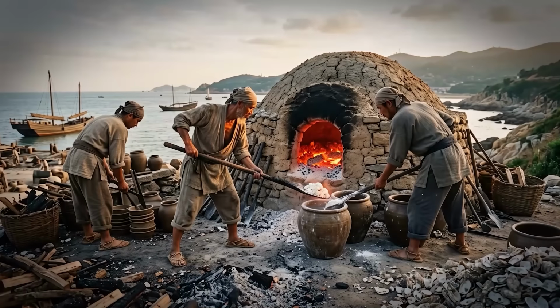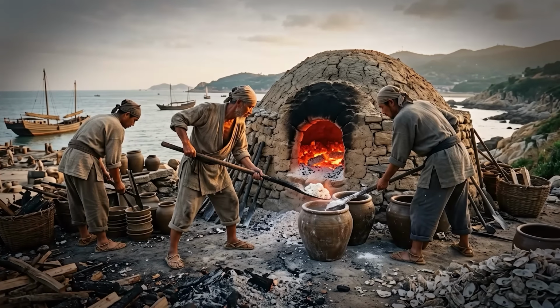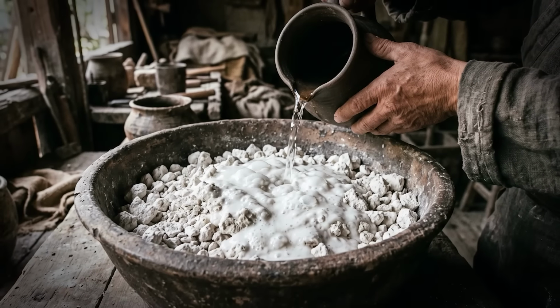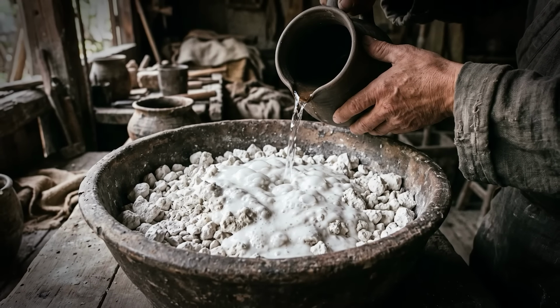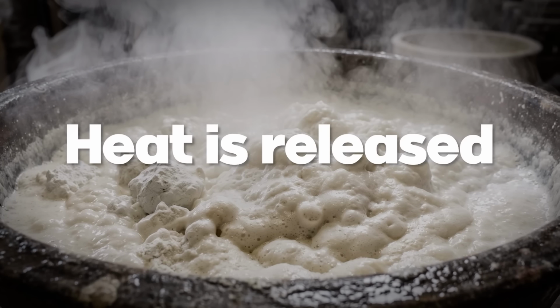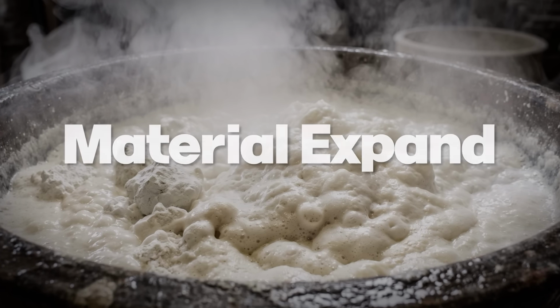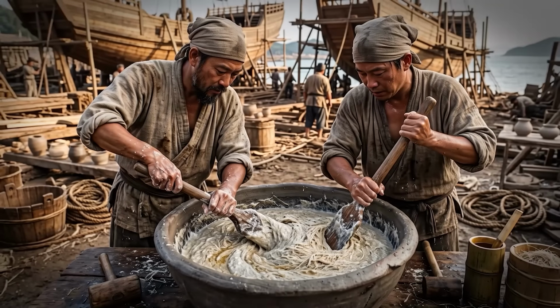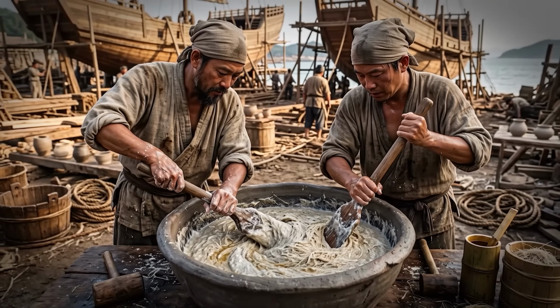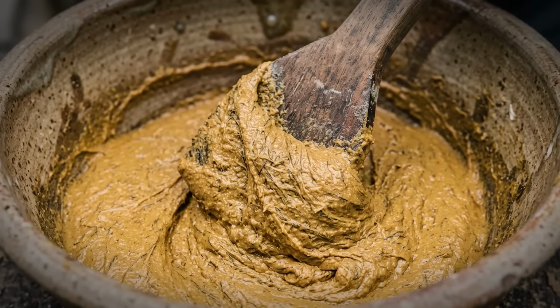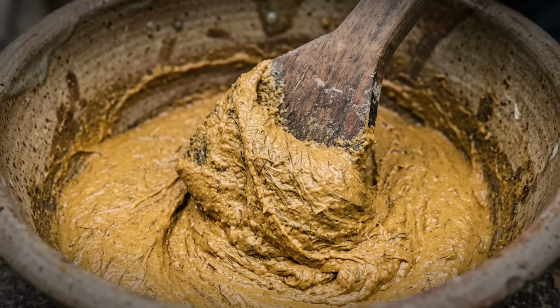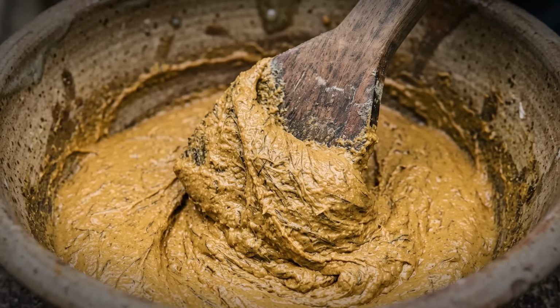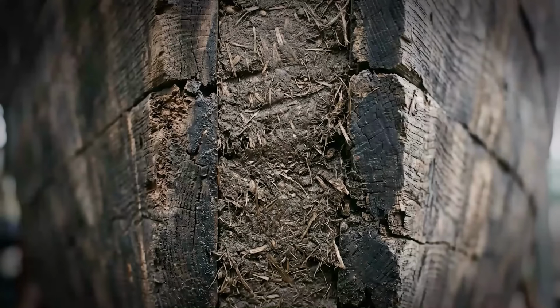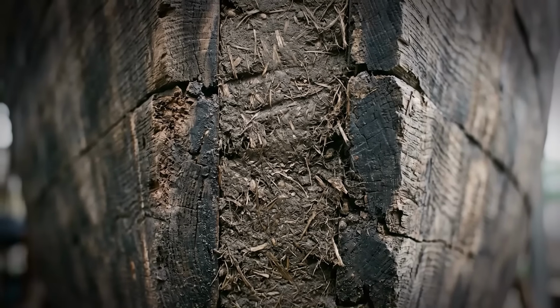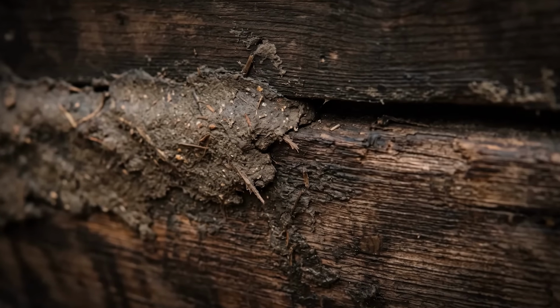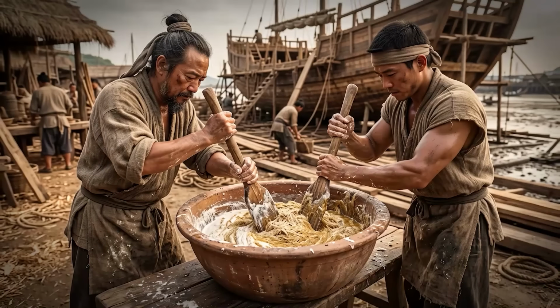When quicklime, the product of burning those harvested seashells, contacts moisture, it undergoes slaking, a violent exothermic reaction. Heat is released, the material expands. When the shipwrights kneaded raw Tung oil together with the lime and the hemp fibres, the calcium ions from the lime reacted with the fatty acids in the oil to form calcium carboxylates, a hybrid bond, part organic, part inorganic, that locked the two materials together at a molecular level. This was not a theory.